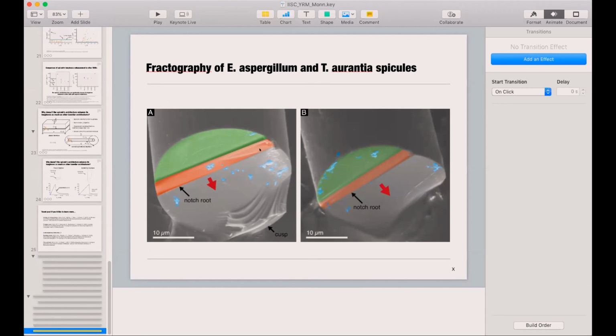And yes, maintaining straightness was very tricky, and that was part of the reason we cut the notch in 2 steps, and it was also part of the reason we had a lot of trouble with getting down the process conditions for the ion cutting in order to maintain the straightness of that notch. This is great. Thank you very much.